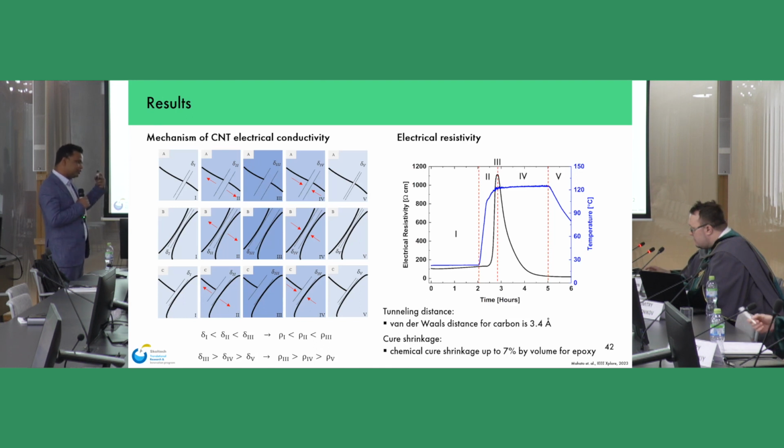So, when viscosity decreases, it's very easy for resin to flow in channels compared to higher viscosity. So this change in temperature, which leads to change in viscosity, is the cause for such change. So if we take epoxy without initiator, or let's say some stable case of epoxy without further polymerization, and we just heat it with the system, it will also increase the tunneling distance.